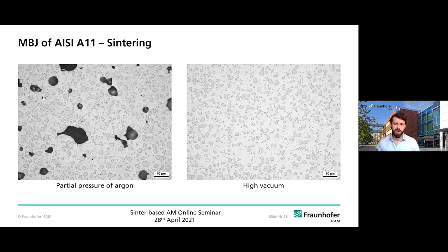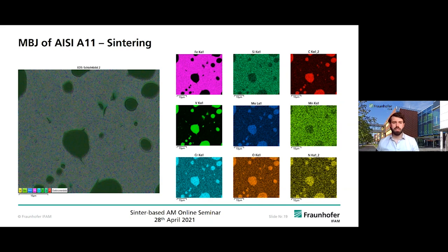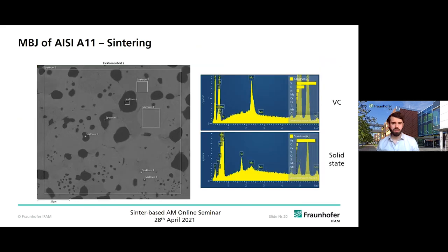And when we went to the microsection and did the SEM samples, we did not see any changed microstructure and element distribution compared to the base material. So that was a really desirable atmosphere for us. And as we were dense, it was perfect for this material and for this parameter setup. The vanadium carbide had a really low content of nitrogen, which was from the base material, and the matrix material had all the same chemical composition.